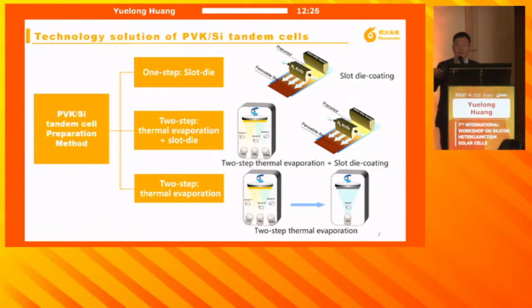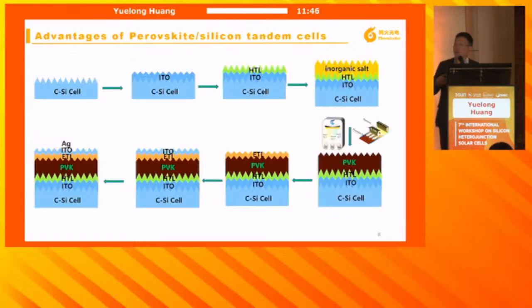So actually, if you look at the publications, the highest efficiency tandem solar cells are usually made by a one-step process. But if you want mass production, it's very difficult to make a one-step process. So more and more companies and teams are using the two-step process, namely first step with thermal evaporation, then slot die. Of course, there are also many teams trying a two-step approach that only uses the dry process. They don't use slot die. So this is the general procedure for two-step, if you combine the evaporation and the slot die.